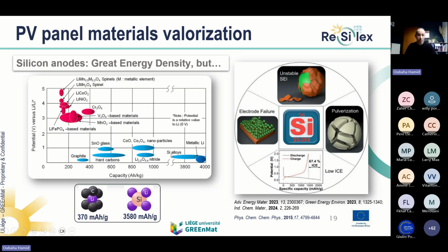However, with these advantages, there are many challenges related to silicon structure. Actually, this silicon is good at storing lithium, but its structure expands by more than 300% during lithiation. So this shrinking and swelling during cycling of the battery leads to the cracking and pulverization of the silicon particles, which leads to unstable particles and electrodes. So the key challenge is to find a way to stabilize this silicon structure.